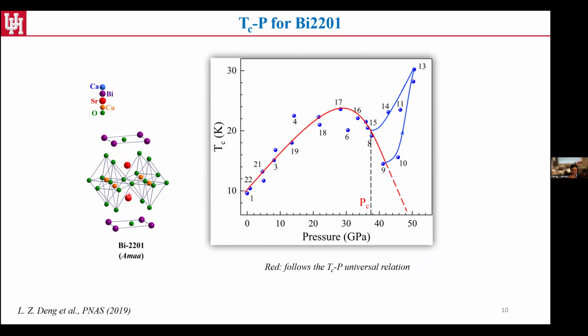So we did study this material and we kept pushing the pressure up. Surprisingly, for the single layer Bi-based cuprate, we also see a Tc increase after passing the first peak, the dome peak. The numbers here indicate the sequence of this experiment. We add pressure all the way following the line, that's the traditional Tc-P relation, whilst it deviates starting from point 10 here, it goes up instead of dropping down. So we do see a hysteresis loop here. It seems that for the single layer Bi-2201, it also has this interesting phenomenon that the Tc can keep increasing beyond the first dome.